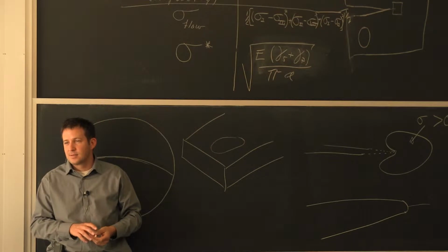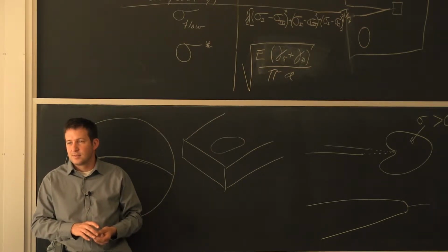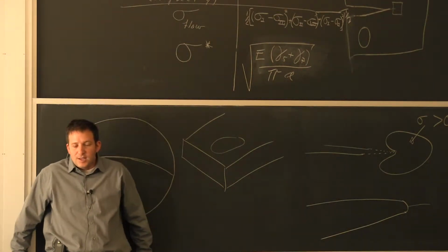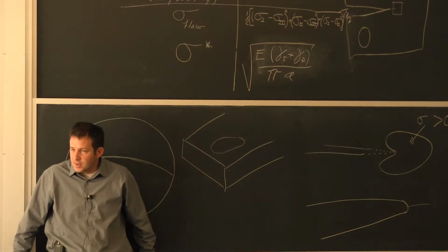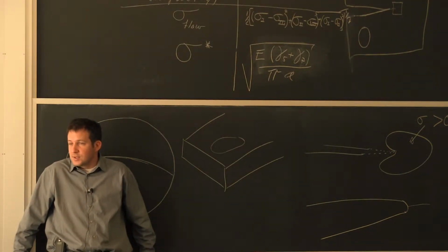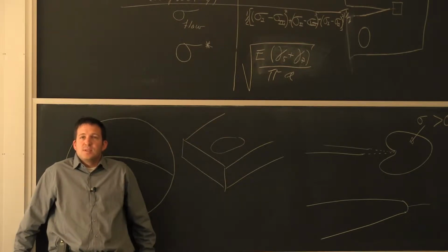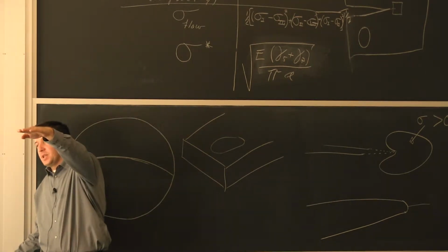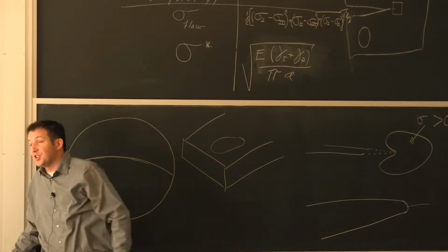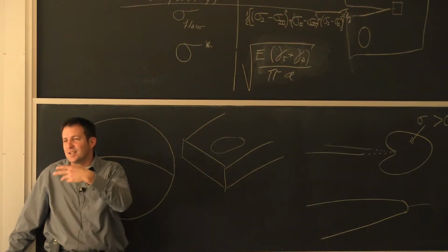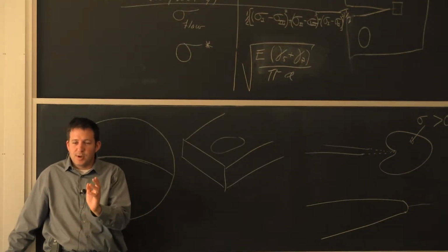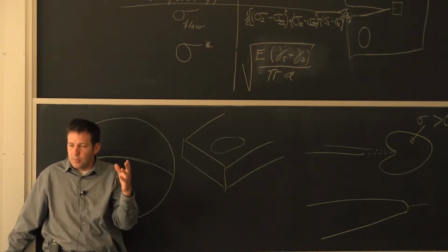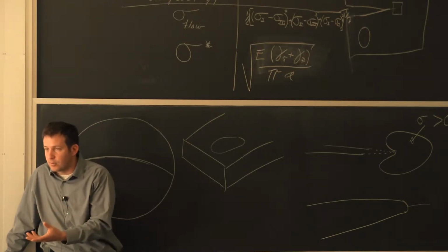Yes? What actually causes that curve to bottom out at the first work hardening? Well, so you have some work hardening in steel, and that's why a lot of times steel is said to have an endurance limit. Although there are some steels, especially if they're welded, that after it's flattening out, they're going to have another failure curve at 10 to the 9 cycles. So there's nothing that's really absolute, and we're going to talk about polymer in the next class. You get away from one way of initiating a crack around a particle.